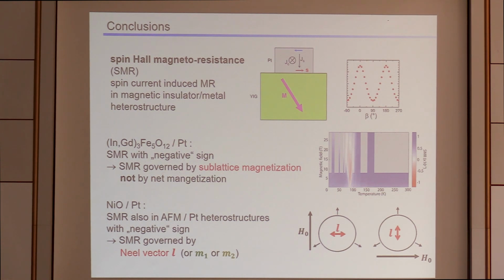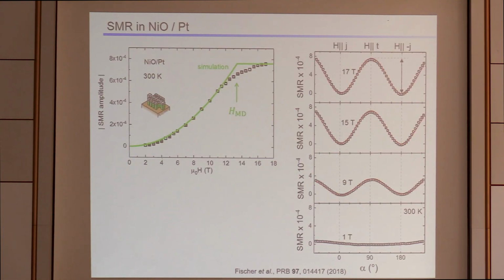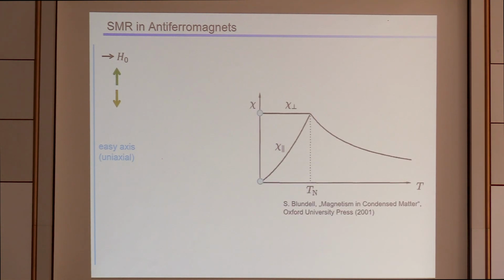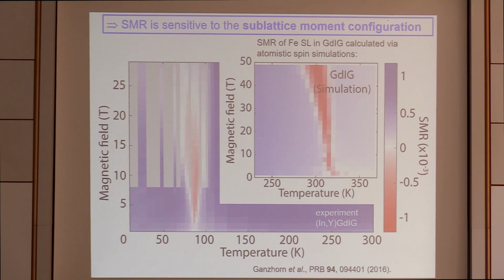If you go back to that slide with the gadolinium iron garnet high field data and the simulations, I thought there was something. The simulation shows 300K, 320, yes, and we see 80. That's a little dirty experimental trick. We thought it would be smart not to use pure gadolinium iron garnet because the pure compound has a compensation temperature of about 320 Kelvin. That's why Joe, in his calculations, uses pure gadolinium iron garnet, the clean phase, and he finds the right compensation temperature.